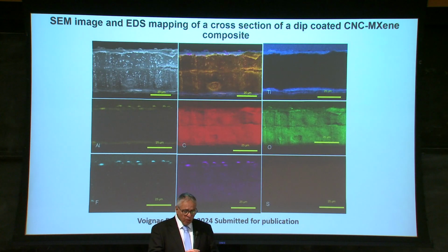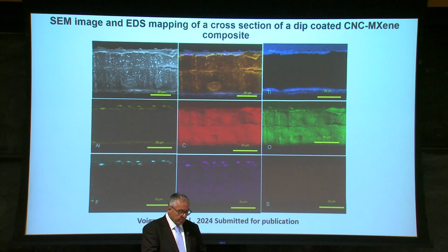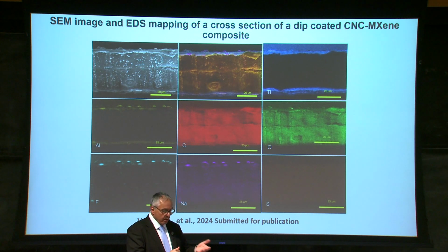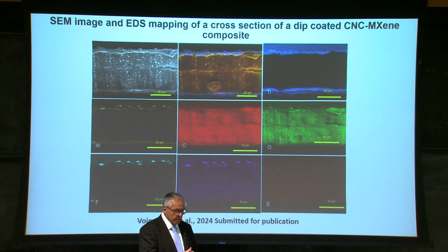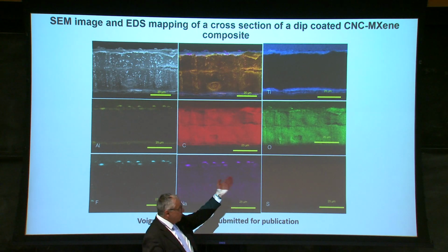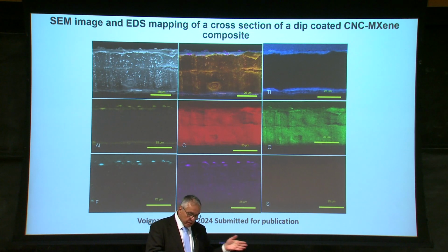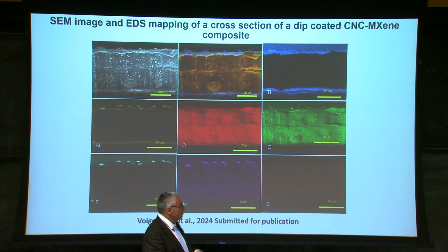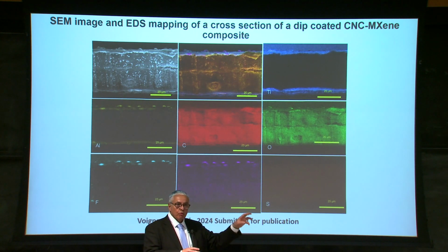When we take all this information, we ask ourselves, just for more confirmation, where is everything? So you can see on the right-hand side in blue is the titanium. We have some in the middle, and on the left, you have a little bit of aluminum, which is part of what's left because, as you know, MXene is made with the assistance of aluminum. In the middle, you can see the carbon, the cellulose, of course, and then the green, the oxygen, so cellulose again. And at the bottom, you can see the fluorine, the sodium, and of course some sulfur here, which indicates sulfate groups on the cellulose nanocrystals.